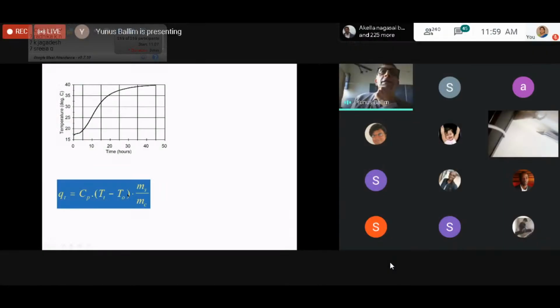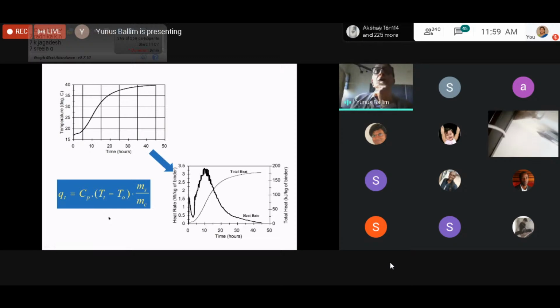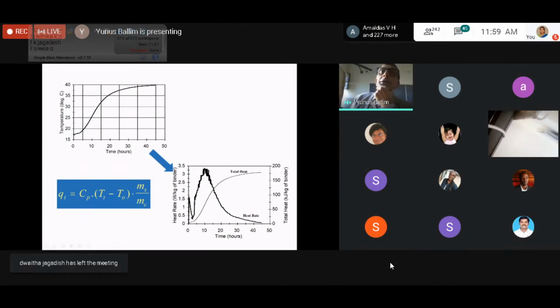Nevertheless, using this equation which I showed you a little earlier, that's the change in temperature term, you can transform that into a total heat function. And if you differentiate that curve, you will get a heat rate, which is really similar to the de la Roy curve I showed you a little earlier. Initial activity of the aluminate phases, cooling down period, and then initial set happens, and then you get mainly alite, or tricalcium silicate hydrate, and then a declining limb with mainly dicalcium silicate hydrate. You see the heat rate in this case.